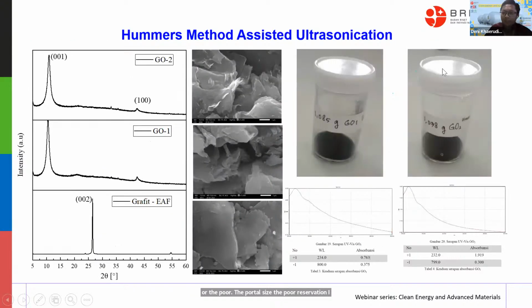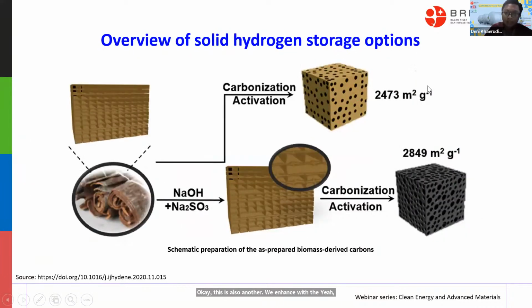Okay, this is also another of our results, regarding enhancement with ultrasonication. Maybe I will just skip it. And this is from another research actually. They used a biomass base, carbonization and activation, I think activated carbon. So they successfully used this catalyst, NaOH and Na2SO3, in order to deteriorate some cellulose and lignin on their surface.